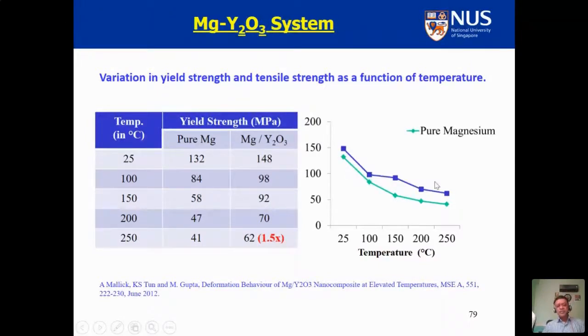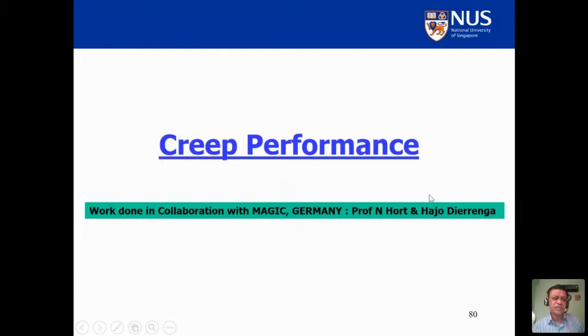Now, if you look at aluminum-based materials, most of them are used at a temperature less than 100 degrees centigrade. Similarly, if magnesium has to replace them, maybe it will be used up to 150 degrees centigrade to start with. And in that range, they are definitely better than the monolithic material. So the reliability and the durability of your component under that condition will increase.